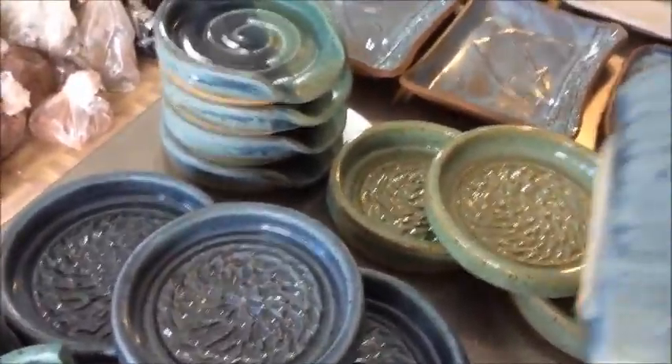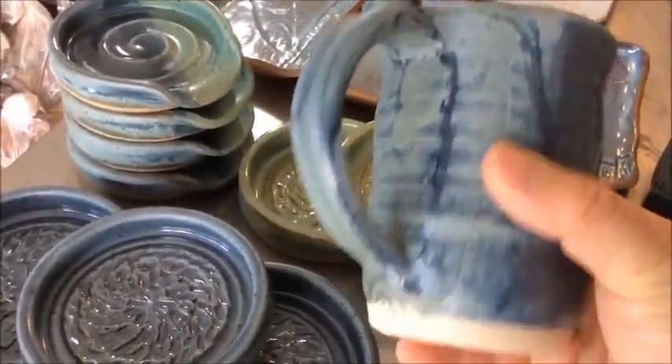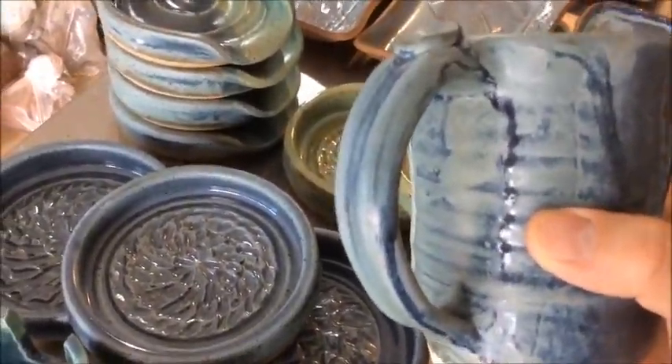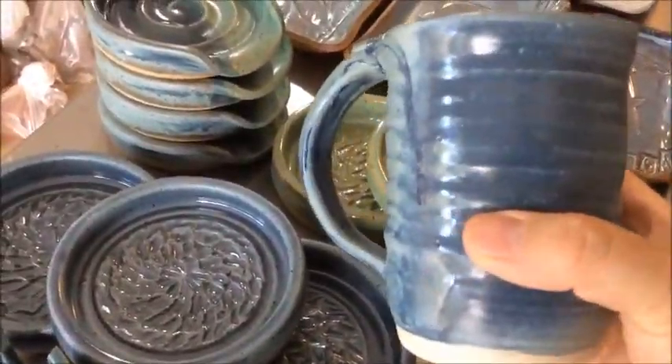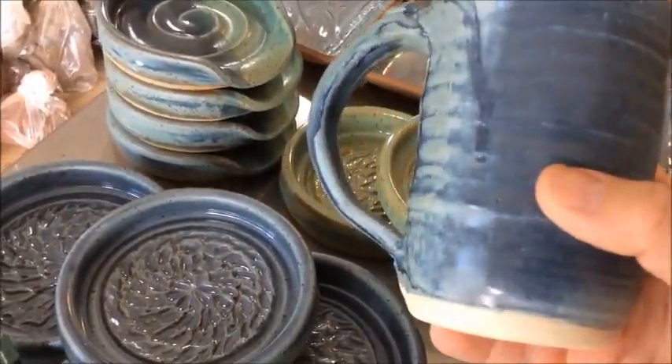Here's a mug — that is probably more like a cone 5. You can see that it's more matte, kind of more of a grey blue there. And on this side where it was probably hotter, you can get that sort of denim shiny blue look.